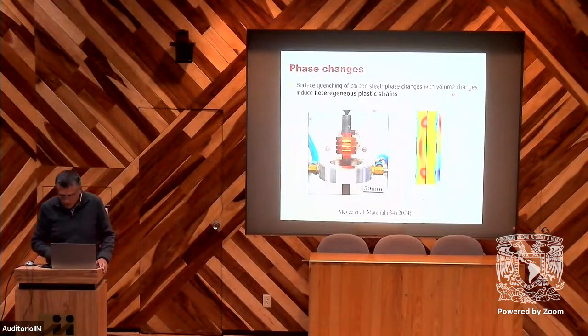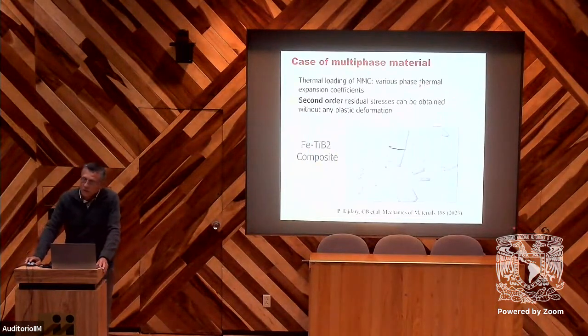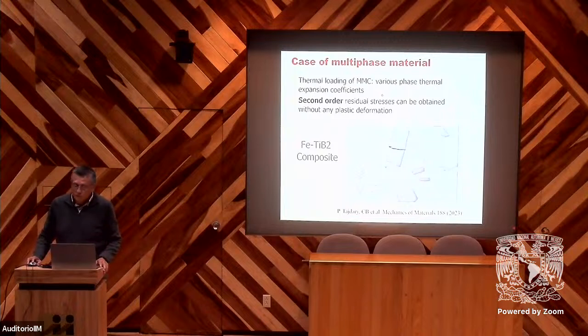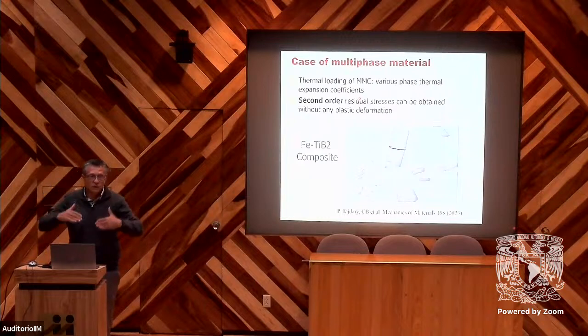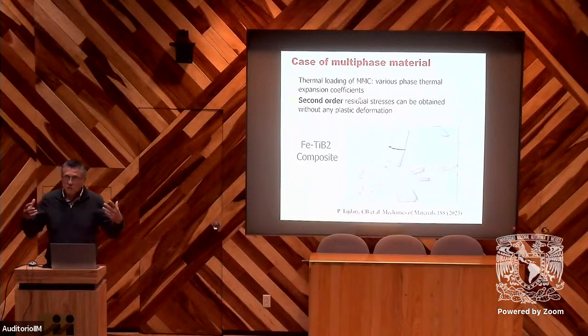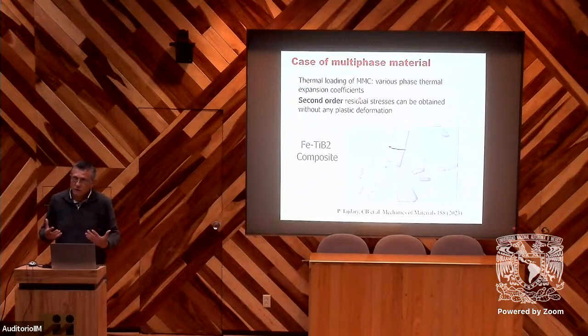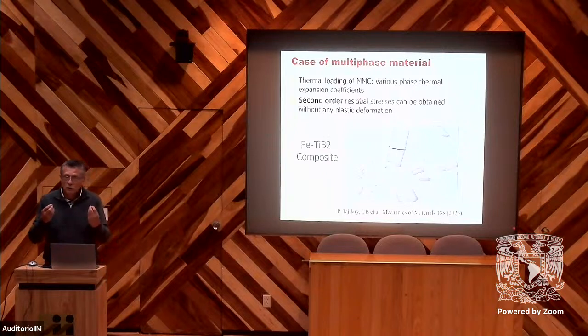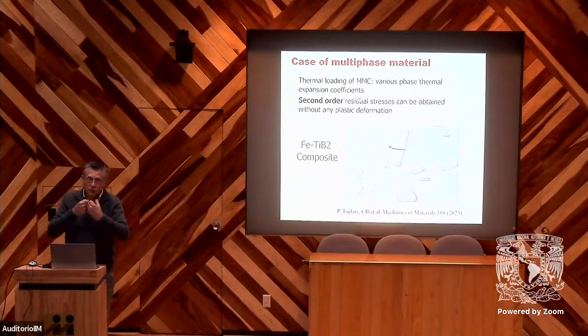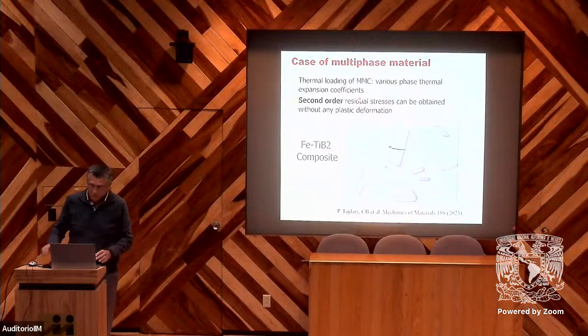And at the end, we have another effect. It's a very particular effect, in the case of metallic matrix composites, where we can have different phase thermal expansion coefficients. And of course, when you change the temperature, we don't have the same expansion, so we will have residual stresses. We call these second order residual stresses, because they are due to the difference between the behavior of two components of the material.